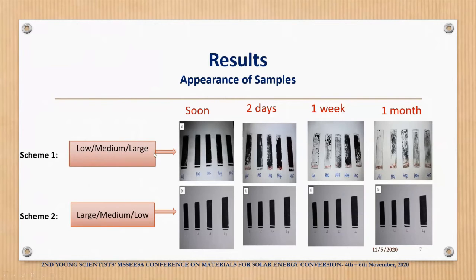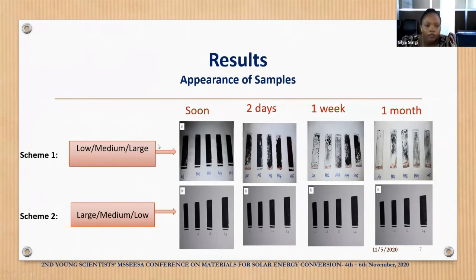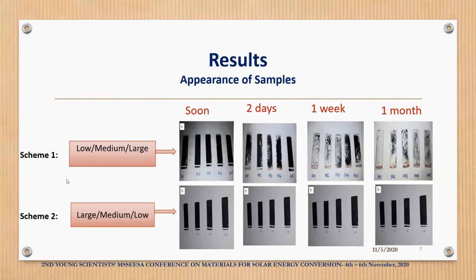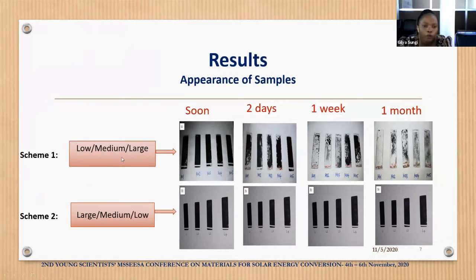Appearance of samples. This slide shows the appearance of samples from each scheme, soon after deposition to 1 month after deposition, whereby scheme 1 of low, medium, and large shows the difference in appearance from day 2 to 1 month, whereby the molybdenum peeled off from the glass substrate with time.